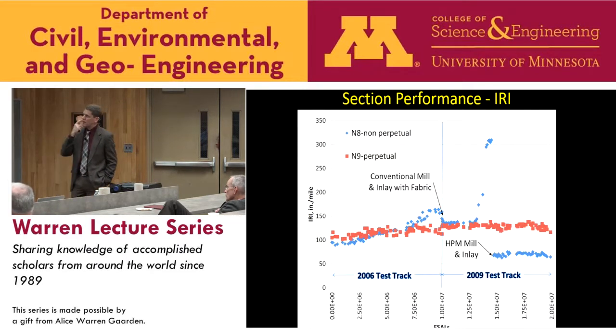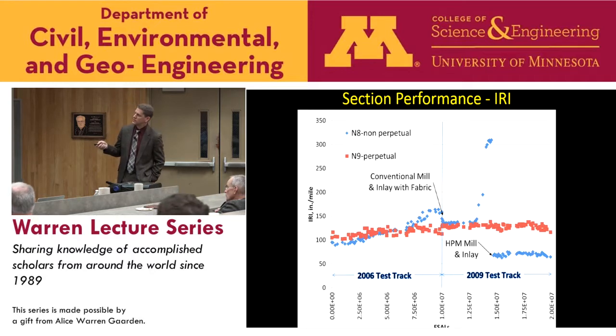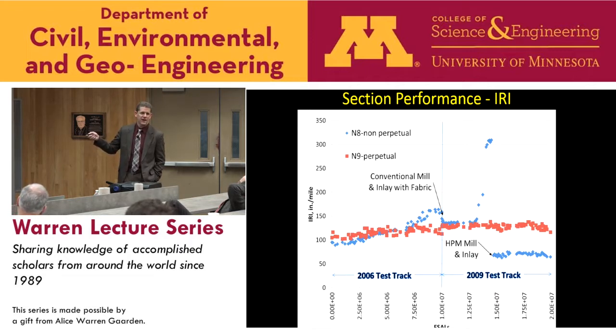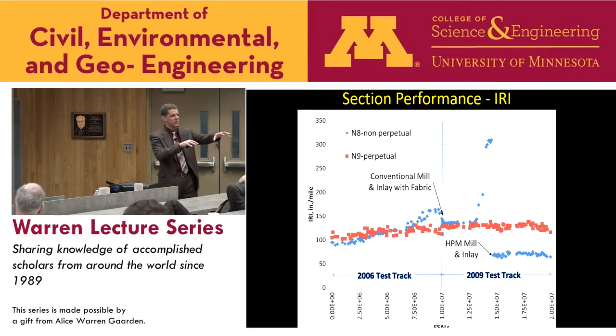So this is showing the roughness of the pavement, and there's two test cycles here, the 06 track and the 09 track, 10 million ESALs in each. In section N9, there's not really a change in the roughness over time. I mean, it increases a little bit, but it's still below the cutoff. N8 got very rough, and then we did the first mill and inlay, and then it got over 300 inches per mile. This is where you're having to divert yourself. If you're driving a road that has 300 inches per mile, you see obstacles in the roadway, and you're swerving to get around them. And then we did the high polymer mill and inlay. It brought it back down and has been very smooth since then.